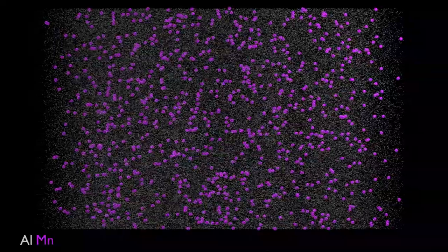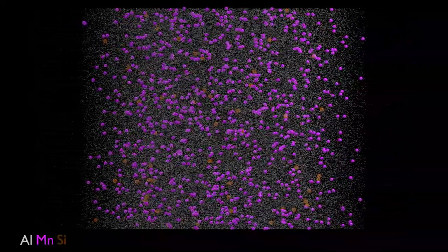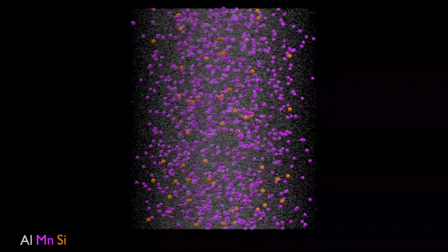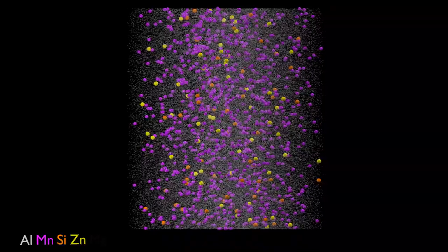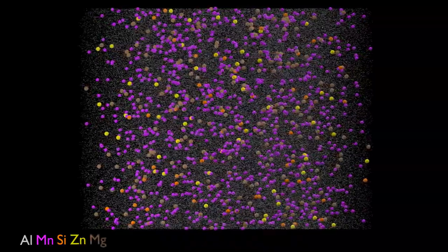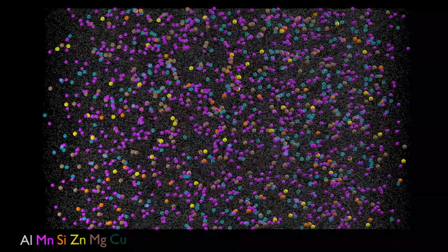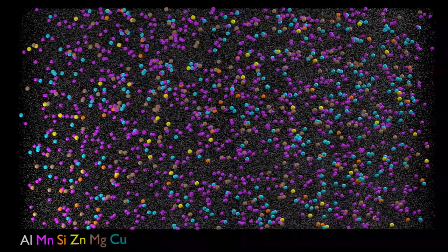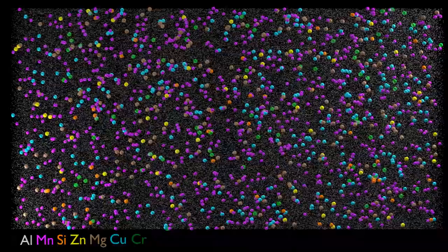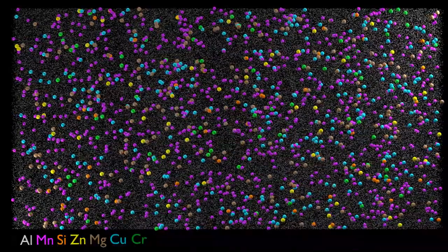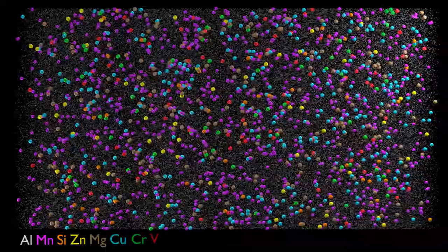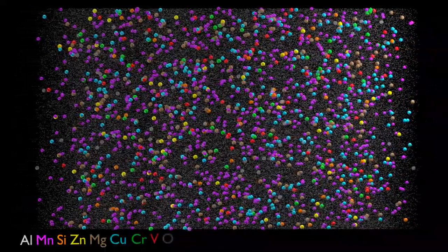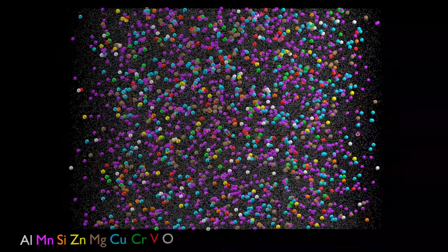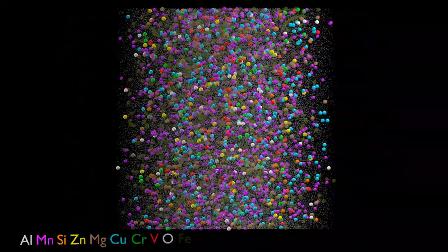This movie gives an example from a research project on impurity-tolerant aluminium alloys. It shows data from a tomographic atom probe measurement conducted on a 3000 series manganese-containing aluminium alloy used for drinking cans. Atom probe tomography is a method that allows to measure the chemical composition of complex materials at the near atomic scale. It works by combining ionization and field evaporation of atoms from tip-shaped sample surfaces under high electrical fields, combined with a mass-to-charge flight spectrometry and a position-sensitive multi-channel plate detector.